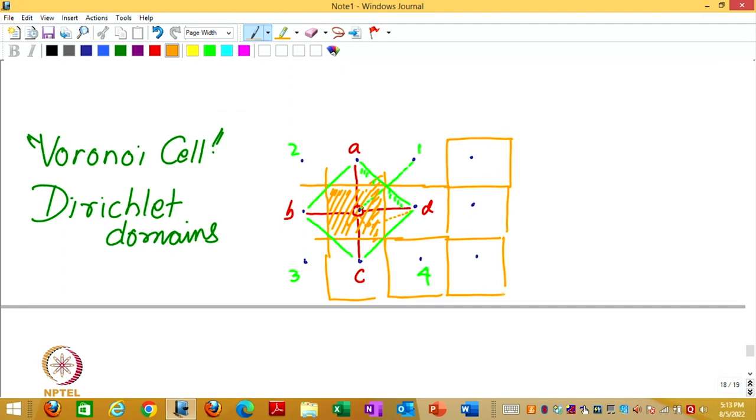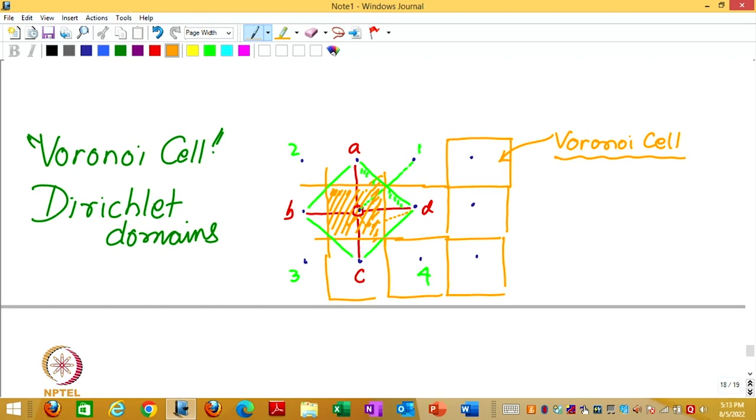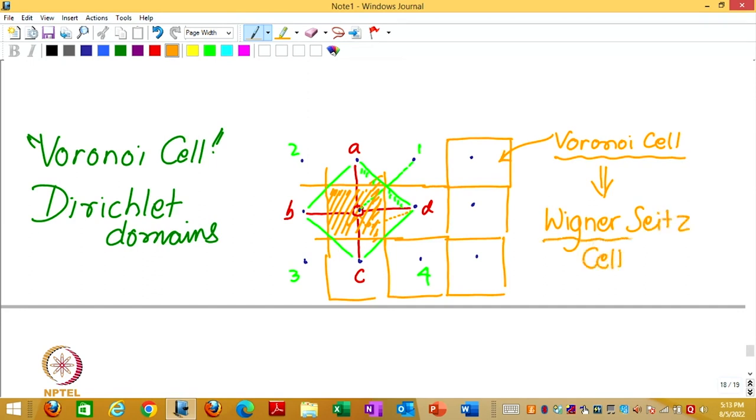What will be the property of this orange square? This is what is called a Voronoi cell. Voronoi cell in mathematics is a little bit more general because it can be made for non-periodic set of points also. But when done for periodic sets, in crystallography a special name is given: a Wigner-Seitz cell. We have constructed a two-dimensional Wigner-Seitz cell for a square lattice.